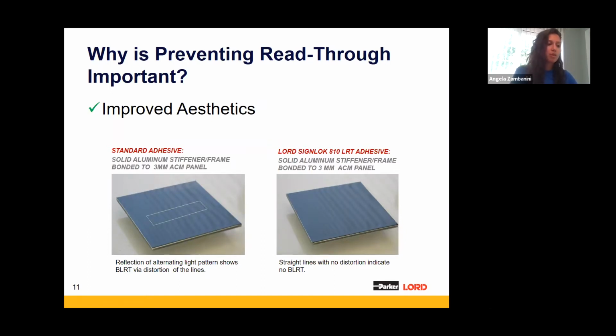So here's another example of what read-through looks like. We bonded a bracket to ACM, which is used for architectural cladding, which I'll talk about more in another slide. We bonded it both with a competitive acrylic as well as the Lord 810. We then reflected window blinds on each panel to see how the reflection would look after the adhesive cured. As you can see on the left, the window blind reflection is wavy, indicating how much the adhesive is distorting the area on the other side. You don't see this on the Lord bonded panel. Instead, you see a nice, smooth window blind reflection.